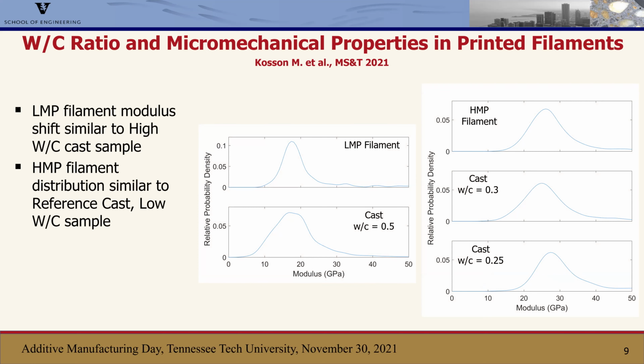So that suggests that what we're seeing as we extrude is that there's a big change in the availability of the water within the structures, and that's changing the mechanical properties of those filaments once they've been hardened.